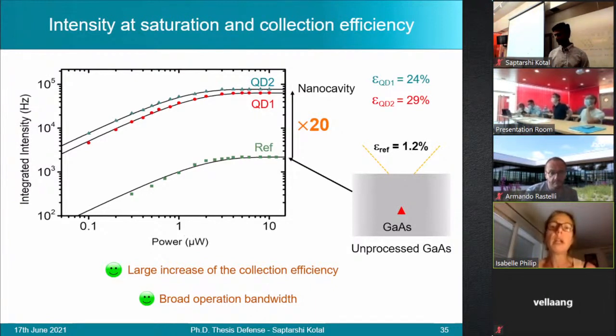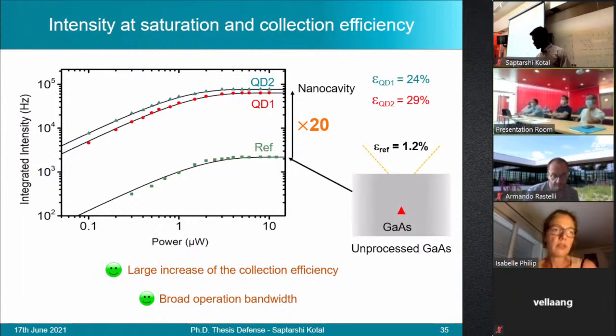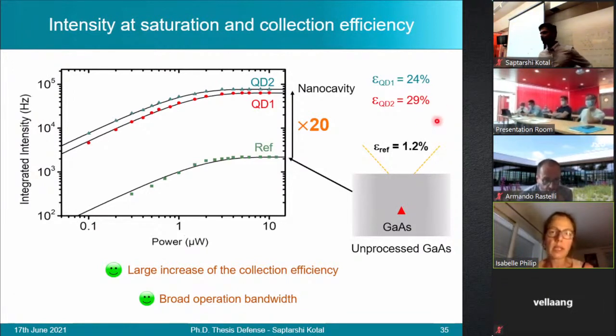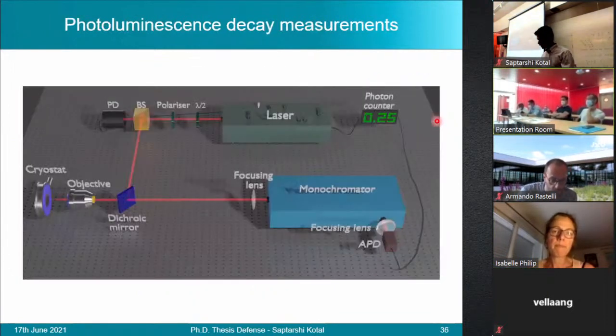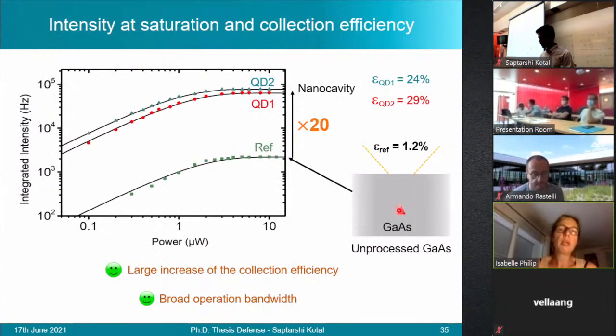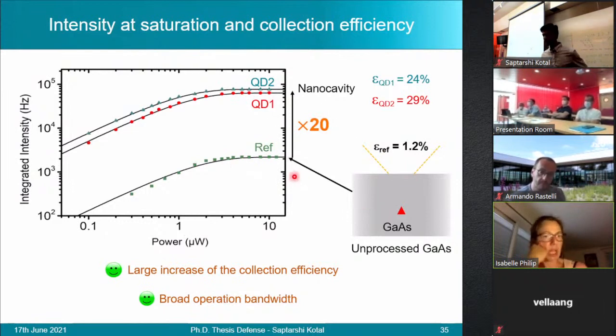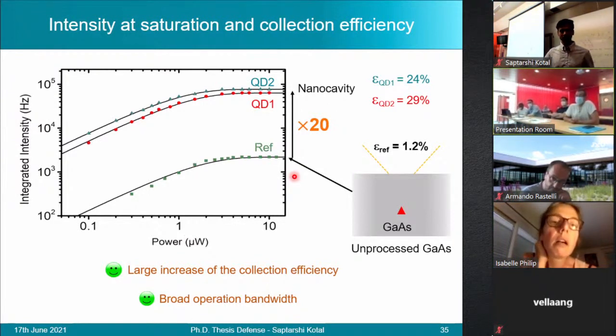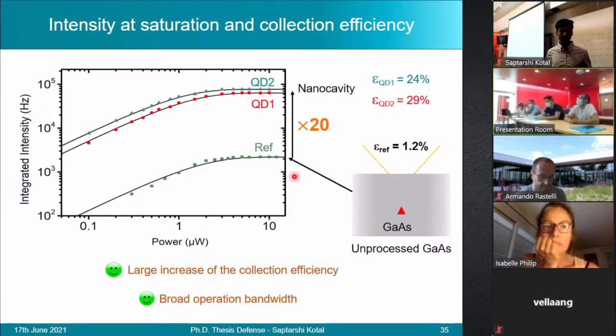Do you have a strong dispersion in the collection efficiency when you go to the bulk or to the nanocavities? Or is the variation in the number of counts that you get at saturation very small? Is it roughly the same, or does it vary? Just for instance, for the reference sample in green, if you repeat the same experiment on, I don't know, 10 dots, you always get roughly the same integrated intensity at saturation, or is there a difference? There has been a bit of a difference, but here I show only one of the dots just to illustrate. What I did personally was I measured the lifetimes and the saturation intensities on several dots. And the value that I have quoted here is the average value. Okay, this is an average value.